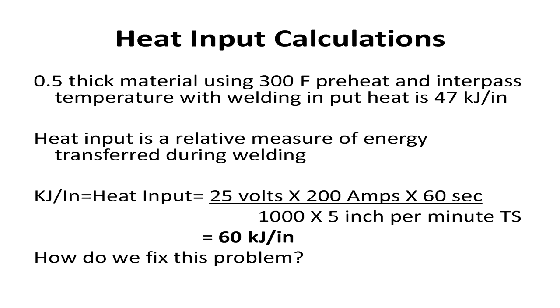All right, here's something. If you read the book on welding this material, it'll say, I copied this right out of a book: half-inch material, preheated to 300, interpass temperature 300, and you can't have a heat input of more than 47 kilojoules per inch. So here's the formula for it: volts times amps times seconds over 1,000, times the travel speed. Well, when I did that, it came up to 60 kilojoules. How do I fix that problem?